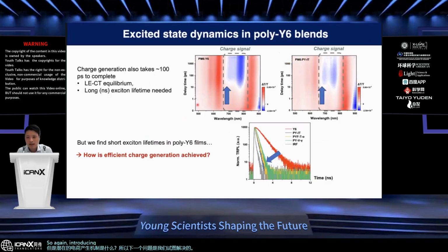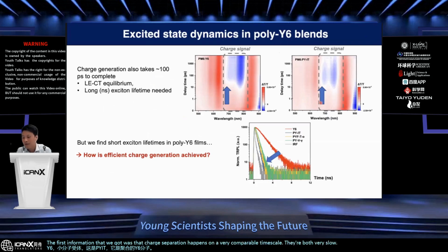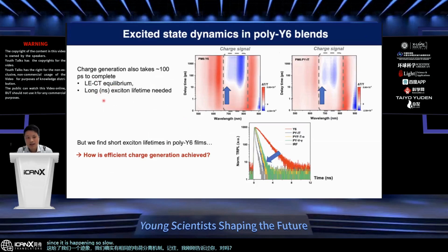So again, introducing transient absorption spectroscopy, we first looked at the charge generation timescale in the blend system. This is the control sample, PM6Y6, the small molecule acceptor, and this is PYIT, which is a polymerized Y6 molecule. The first information that we got was that charge separation happens on a very comparable timescale. They're both very slow and also both temperature dependent. So this gives us an indication that indeed we have just the same charge separation mechanism going on. And remember, I just told you that since it is happening so slowly, we need to have very long exciton lifetimes